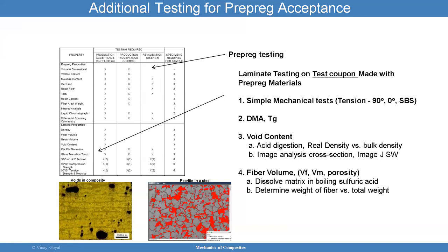And also we will want to look at the fiber volume, which means we need to dissolve the matrix, right? We need to dissolve the matrix in sulfuric acid to then determine the weight of the fiber versus the total weight. And you may ask, what is DMA? DMA is a dynamic mechanical analysis that's performed. And what is the purpose of that?